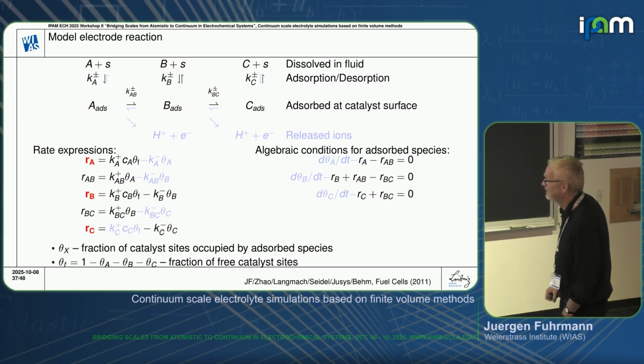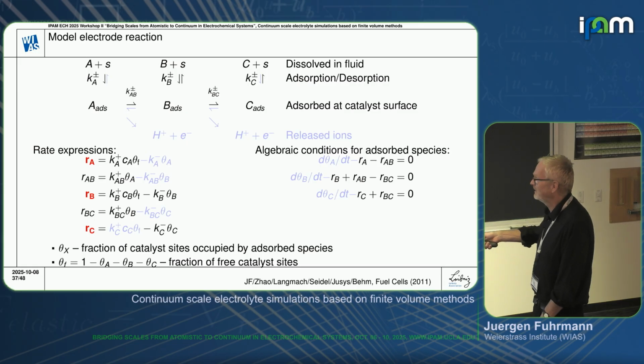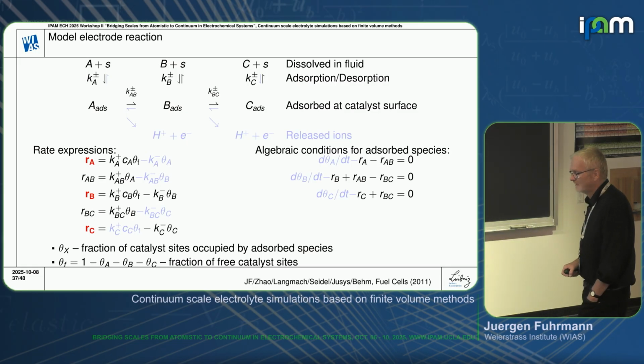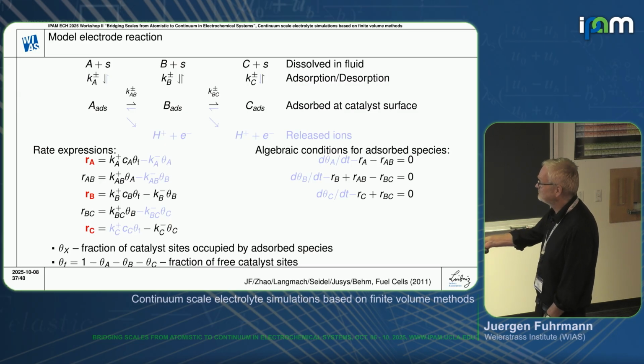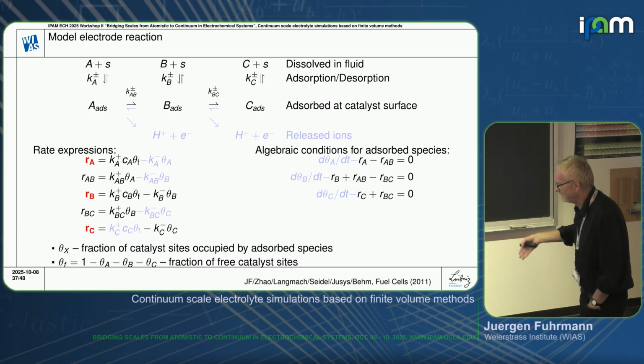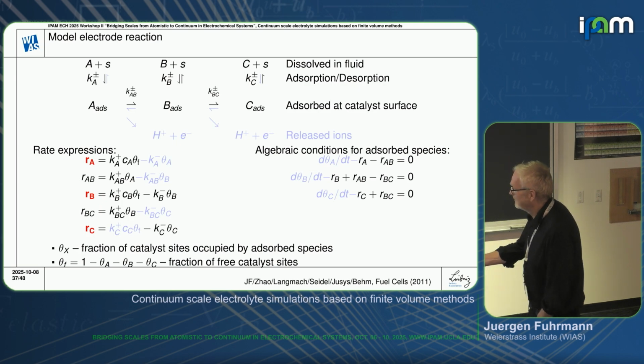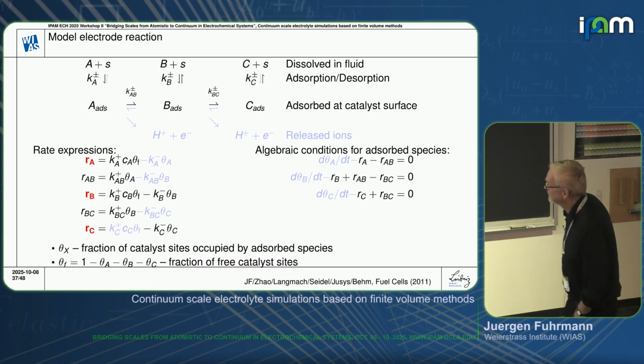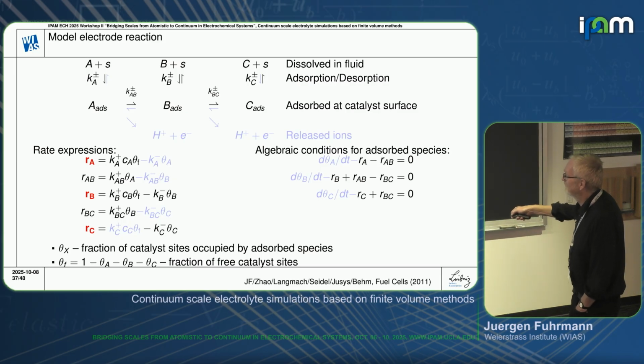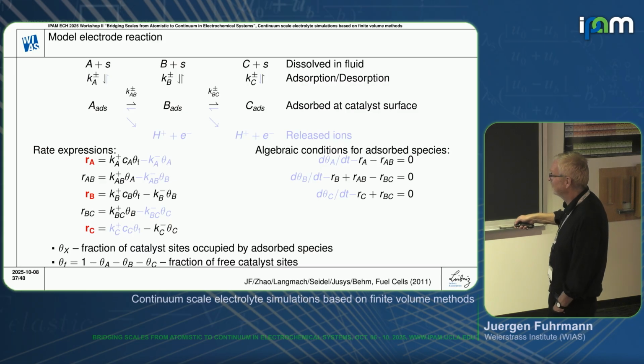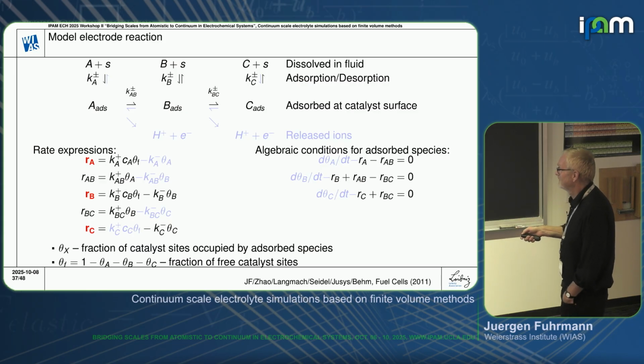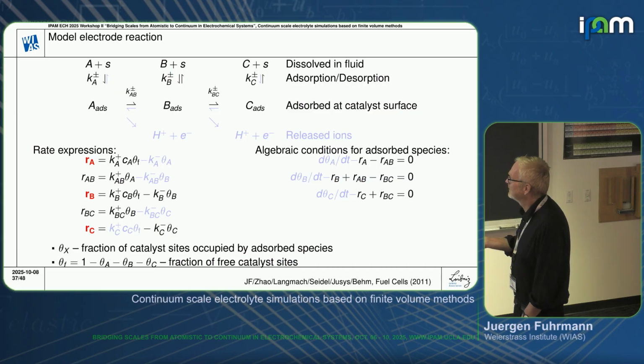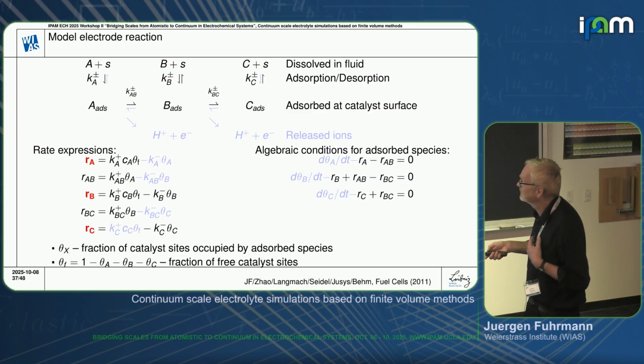So the idea is to just assume that adsorption is a reaction with a free catalyst site, which then results in a catalyst site which is, for instance, species A reacts to theta A, which is then species A adsorbed at the catalyst. And then we can have another parameter here, which is catalyst loading. Then we can set up the corresponding evolution equations also for the concentrations of the adsorbed species, which would be part of the system, which in the stationary case then reduces to an algebraic system. And we then can use our finite volume method and discretize these things and can do the calculations.